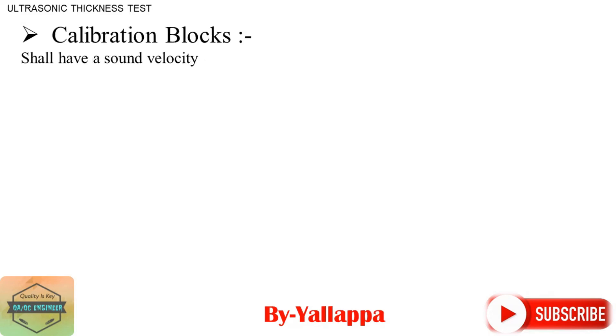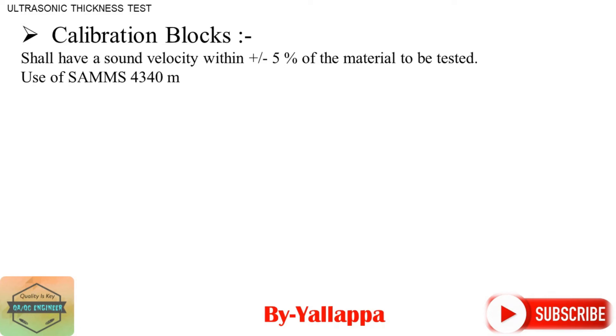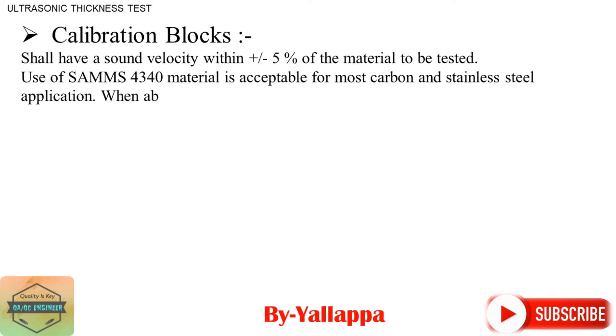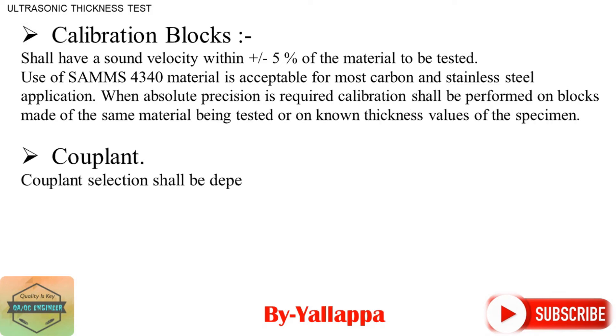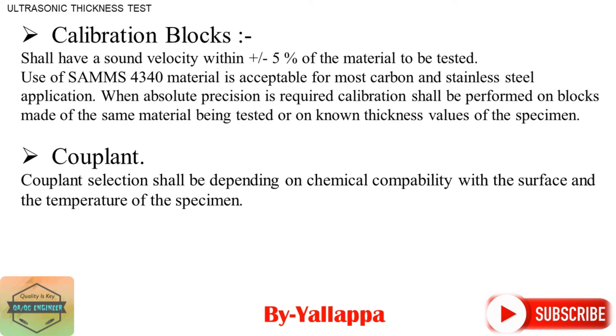Calibration Blocks: Shall have a sound velocity within 5% of the material to be tested. Use of SAMMS 4340 material is acceptable for most carbon and stainless steel applications. When absolute precision is required, calibration shall be performed on blocks made of the same material being tested, or on known thickness values of the specimen. Couplant selection shall depend on chemical compatibility with the surface and the temperature of the specimen.